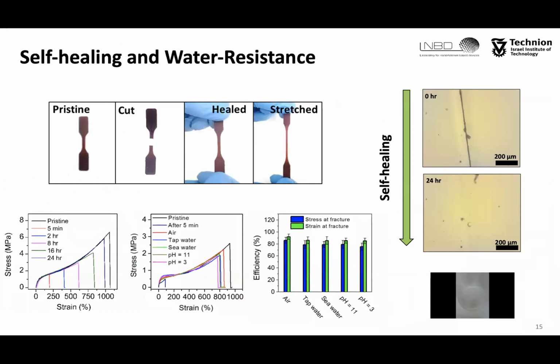In this slide, you can see in the top left images the ability of the polymer to recover its elastic properties after a complete cut. The right images show the full regeneration of scratches within 24 hours under ambient conditions.